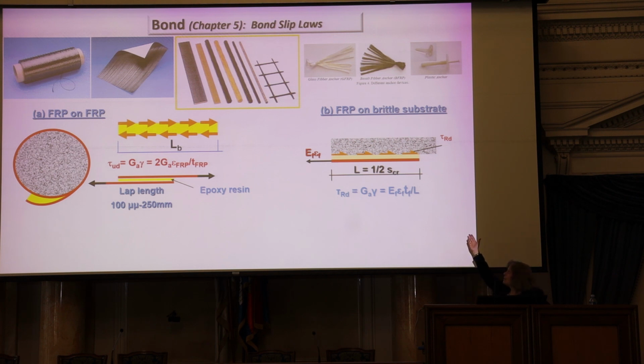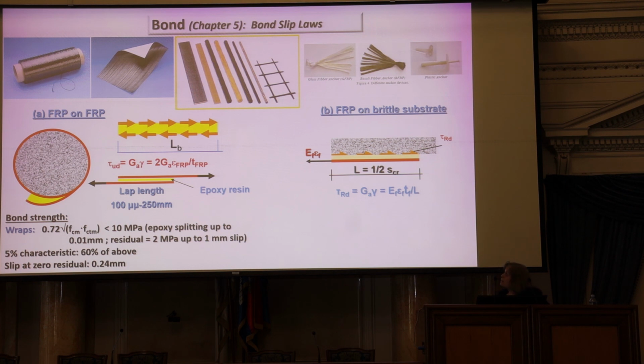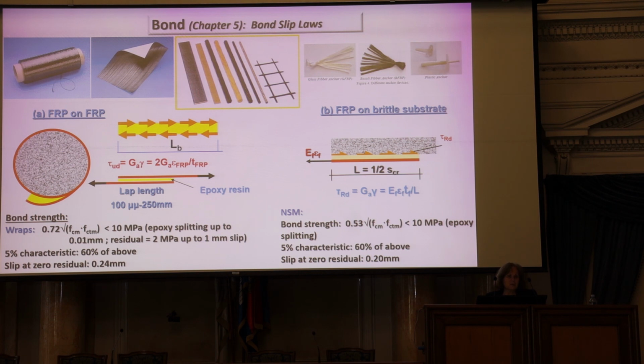So this is the most critical situation where the weakest link gives. The weakest link could be either the layer of adhesive or the cover of the concrete member. So you can have shear failure inside the cover. You can anchor it with these chemical anchors that you see at the top. So you drill a hole, you put this with epoxy, and then you spread the fibers of the FRP all around. That's a very good way of anchoring. Or you can even use dowels. So the FIB Bulletin 90 gives you information about the bond strength of wraps and of near surface mounted reinforcement.